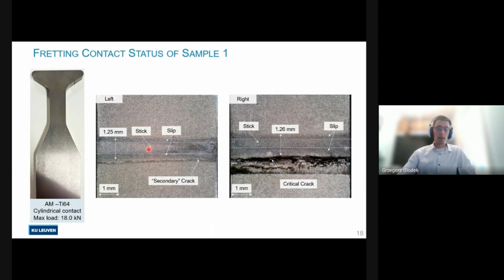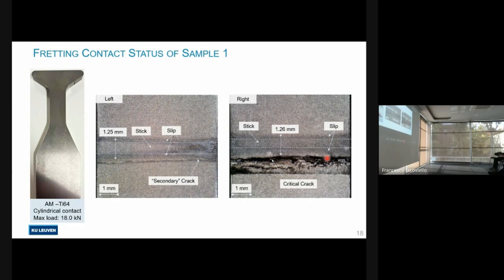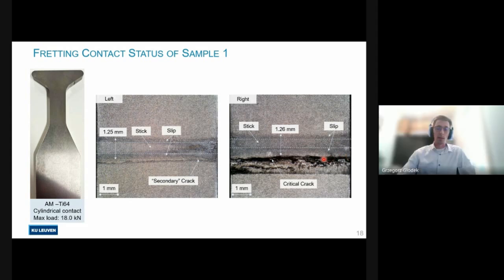So the stick and slip areas are clearly visible. We can also see a crack which resulted in a failure that is present right outside the slip area. Also, interestingly, we can see a secondary crack on the other side, which initiated possibly here at the edge, but hasn't had the chance to propagate since the failure occurred on the right side.